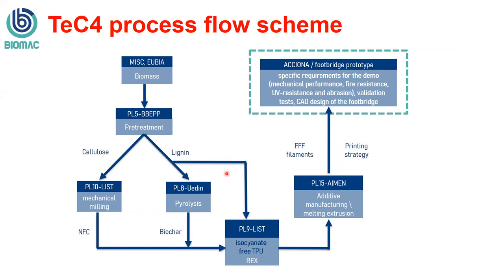And of course, that can have some nice characteristics from the standpoint of mechanical reinforcement and, again, stabilization as well. And we can also imagine taking this lignin, pyrolyzing it to biochar, and using that as a means of, for instance, enhancing the UV resistance or the thermal conductivity of the materials. And so these different nano additives are, again, included in an isocyanate-free thermoplastic polyurethane.